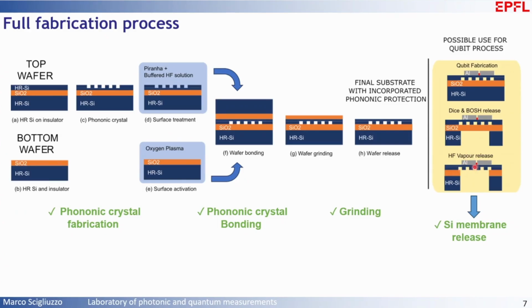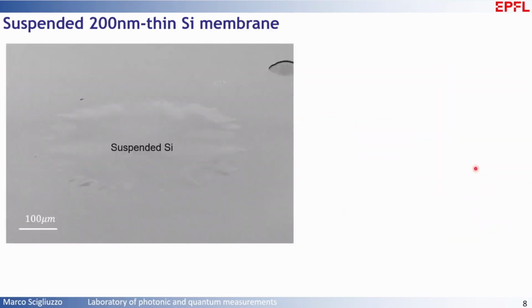So we start from this. We pattern the bottom of the wafer, and we etch with a sequence of dry etch, xenon difluoride, and HF vapor release. And we're able to indeed release, I hope you can see, a relatively large area of a thin, single crystal, 200 nanometer thin silicon membrane, and on a very large scale.